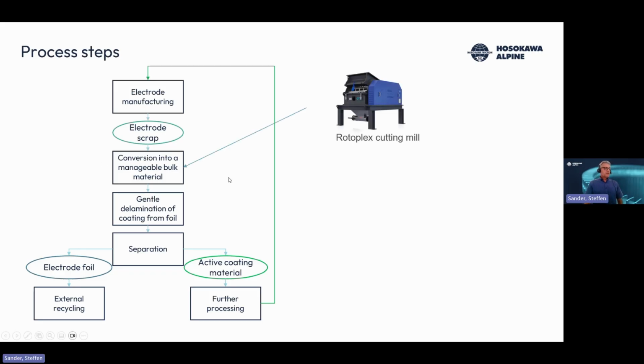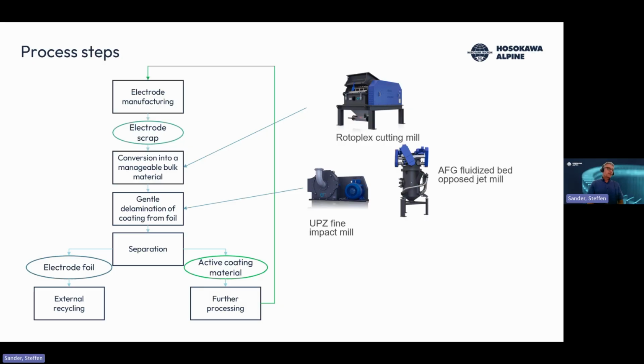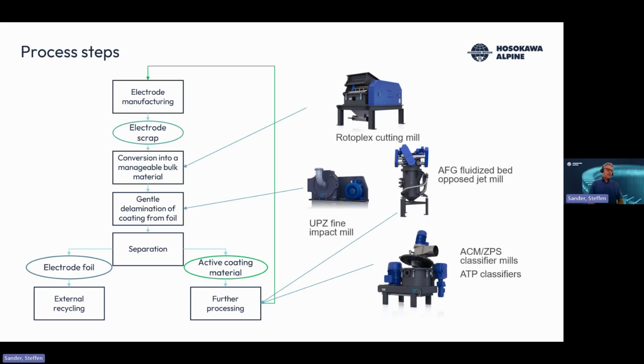For these single process steps, we have different solutions at hand for this conversion into a manageable bulk material of these scraps that are coming from the production. We could use cutting mills that are specially designed to have a low effect on the electrode foil itself, so low degree of impurities and so on. For the delamination, there's two different processes I will show you later on, one using an impact fine mill and the other using a fluidized bed jet mill that is operated in a non-conventional way. And then for the further processing of the material, we have classifying mills available, fluidized bed jet mills. That's basically the same type of equipment that's used for the production of the virgin materials.